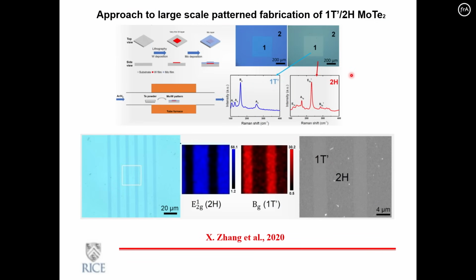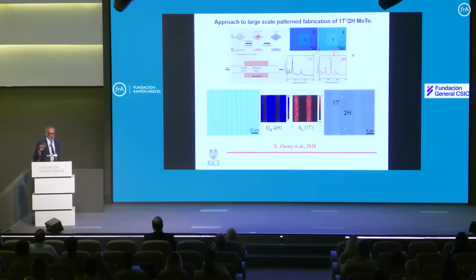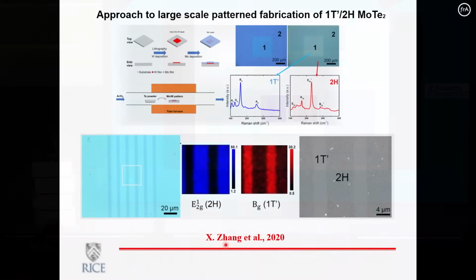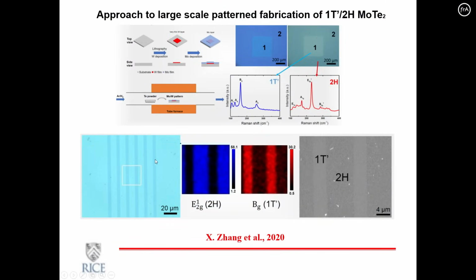Slightly distorted structure, but the lattice parameter is very similar. Everything is similar. One of them, this 2H phase, is semiconducting, and the 1T prime phase is metallic. And again, it's just based on small distortions in the lattice structure. And again, the question is, can I make these arrays of atomically thin layered materials that controllably have regions of one type and regions of the other?